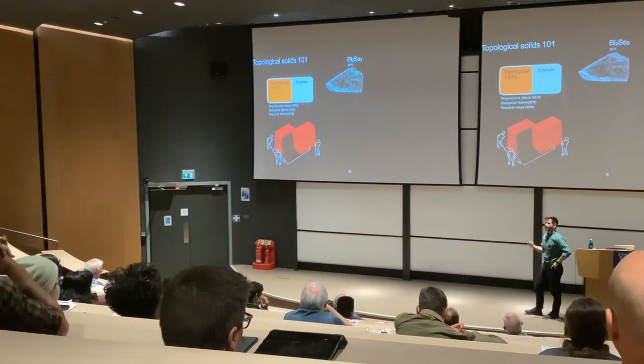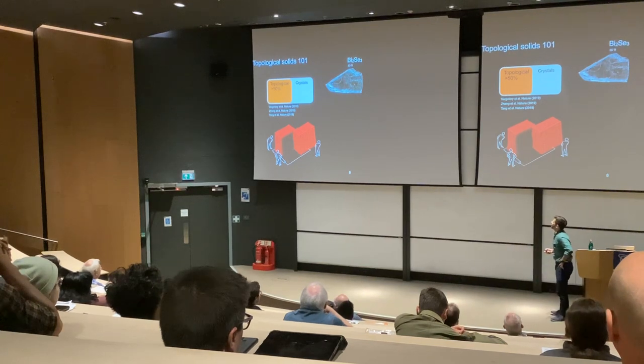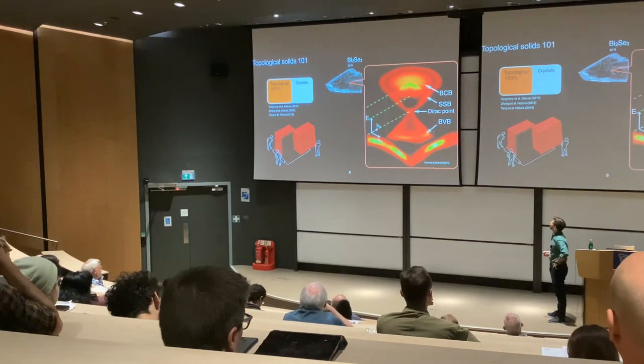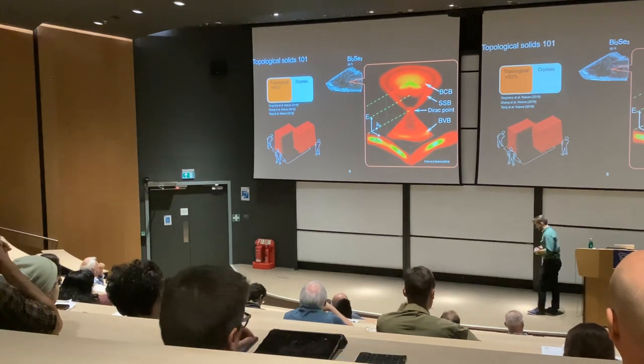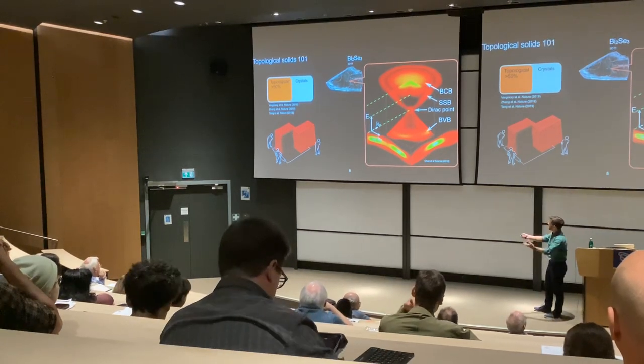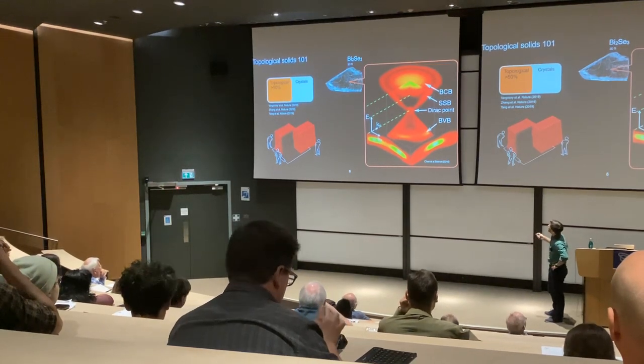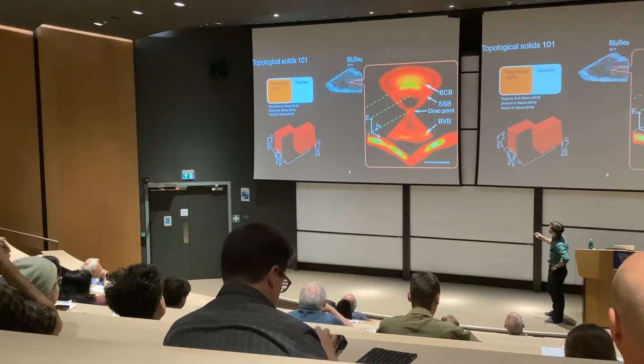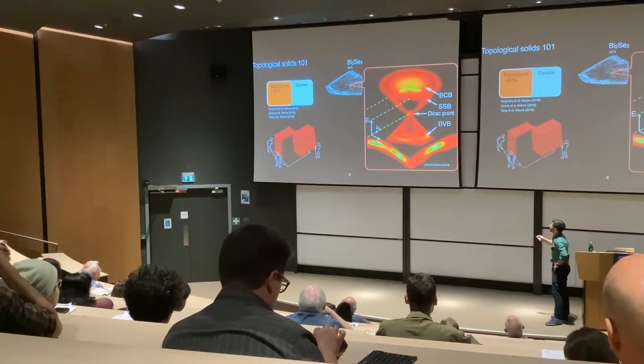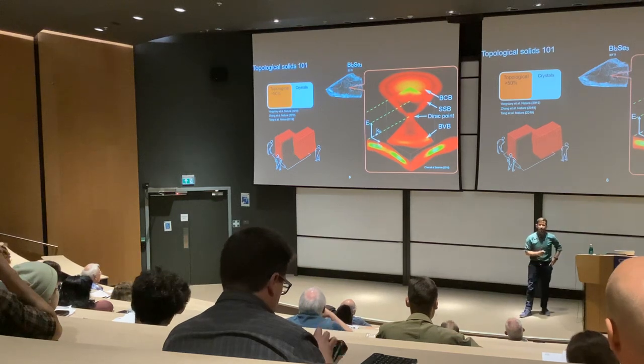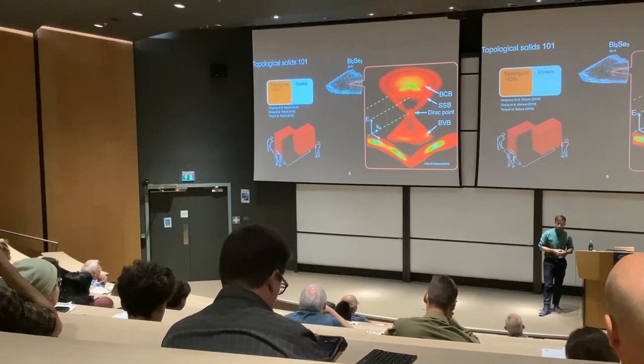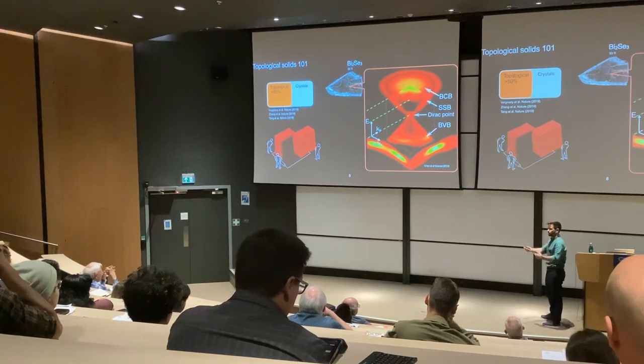How do we study this? We ask how the electron's energy changes with its momentum — essentially how fast they move. You can shine light on these materials and extract electrons, getting plots of energy versus momentum. You see a lot of spectral weight at the bottom, a lot at the top, and something that crosses and connects them in a cone-like, roughly linear way. This is called the dispersion relation.